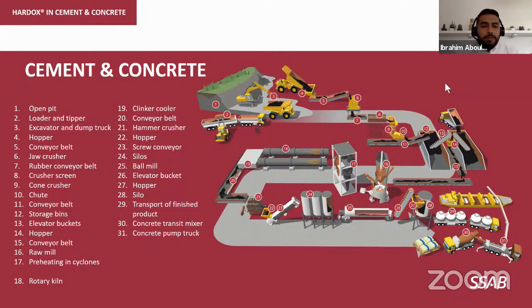Then we move to point number 16, in which we have the raw mill. The raw mill is a machine that usually takes an input of clay, iron, limestone, and fly ash, which become dried and ground at the bottom to be prepared and sent to the preheating, which is step number 17, to go to the furnace, a rotary kiln, later in step 18. In the rotary kiln, we have around 1500 degrees. So you don't have any business for Hardox there, since the material will get softened. We will discuss that also later in the presentation.